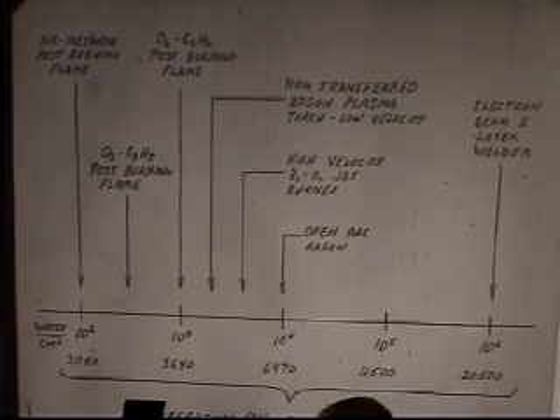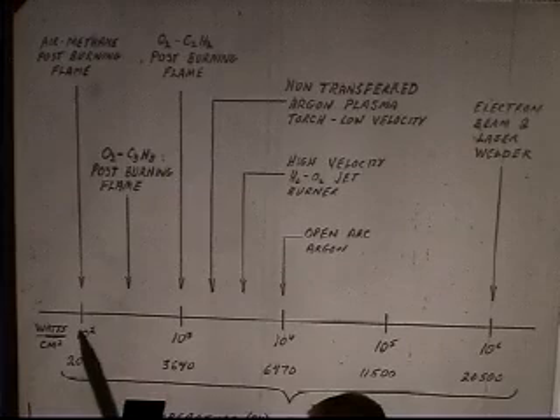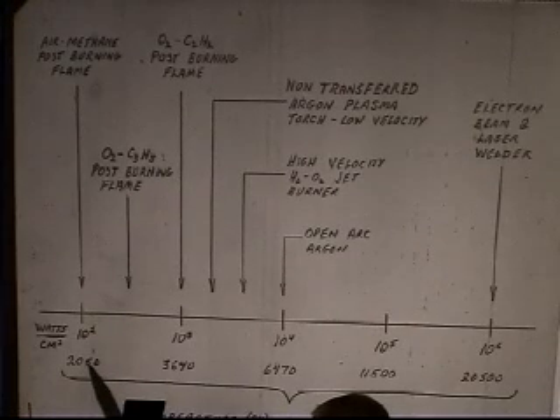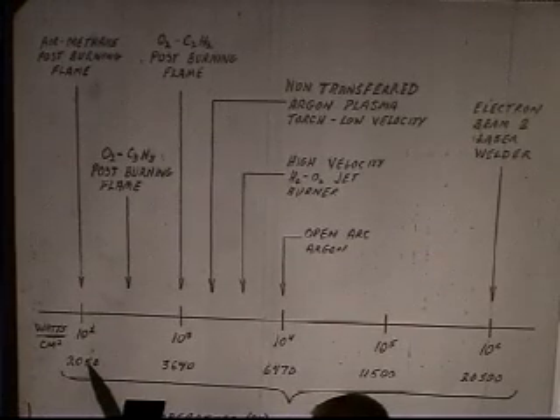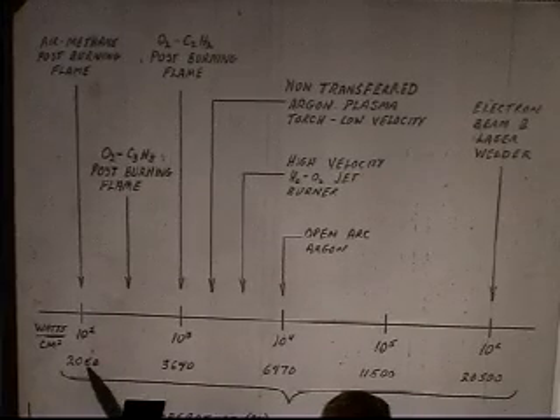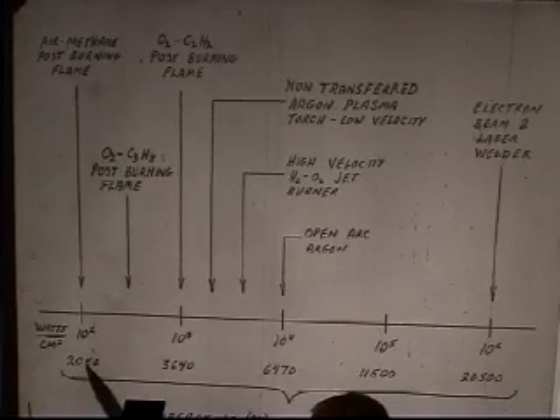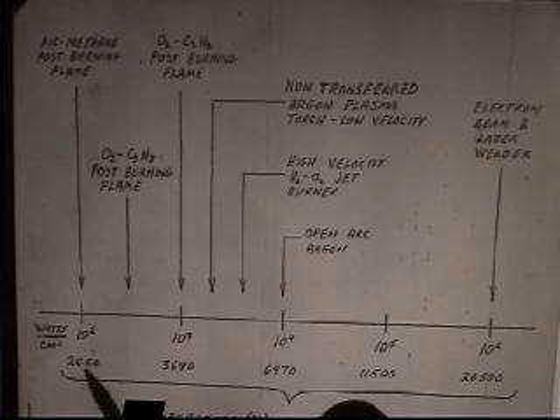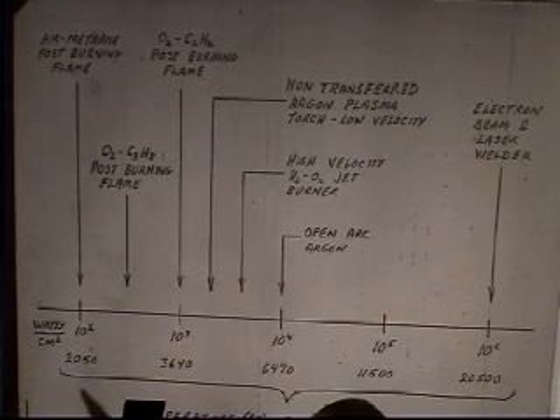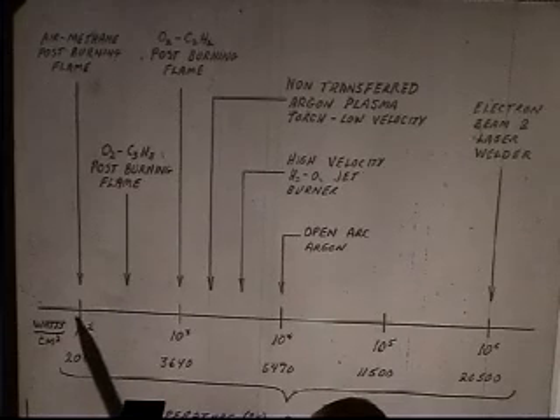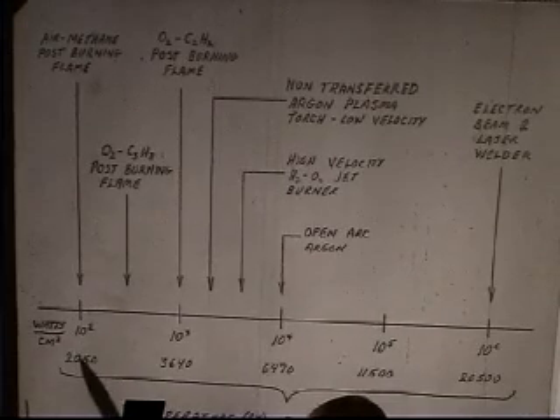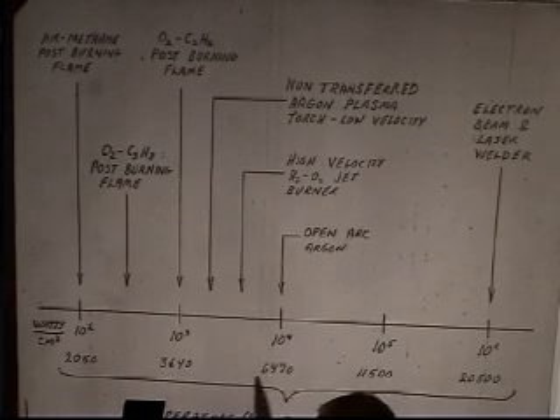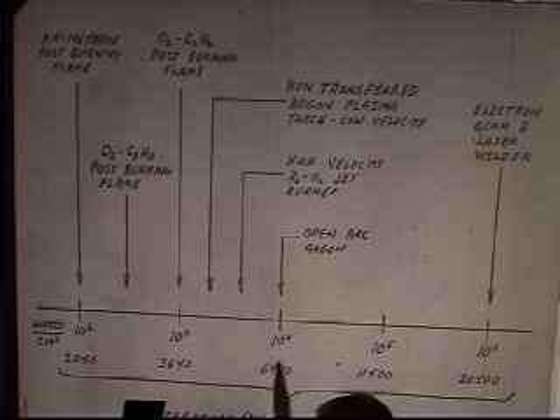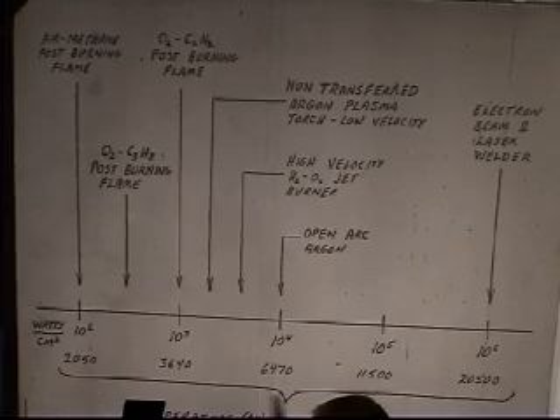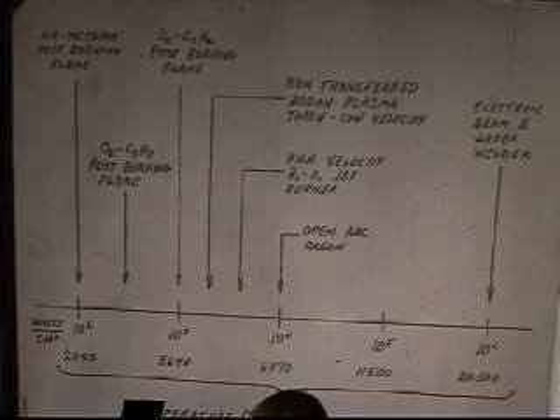He also plots the blackbody radiation temperature. Here, the blackbody radiation temperature is only equivalent 2,000 degrees Kelvin. That's if the surface is radiating away as much power as the equivalent power of 10 to the squared watts per square centimeter. You can see over here, I'm getting to temperatures that'll melt virtually anything, and electric arcs will essentially melt virtually anything. Of course, lasers and electron beams will melt anything very rapidly.